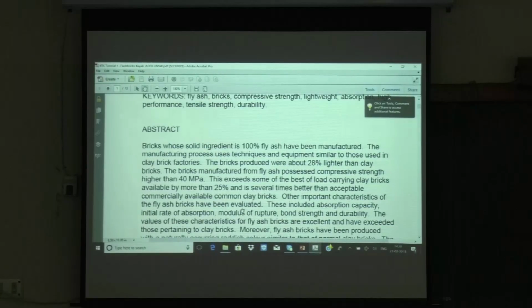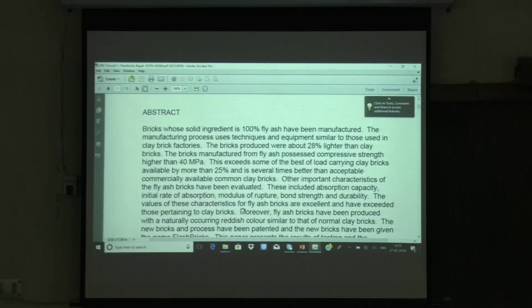This exceeds some of the best load-carrying clay bricks available by more than 25%, and it is several times better than acceptable commercially available common clay bricks. The other important characteristics of the fly ash bricks have been evaluated, and these include absorption capacity, initial rate of absorption, modulus of rupture, bond strength, and durability. These are the essential properties of any brick, and this work showed that all these properties have been evaluated and the results achieved are very acceptable. The values of these characteristics for fly ash bricks are excellent and have exceeded those pertaining to clay bricks.